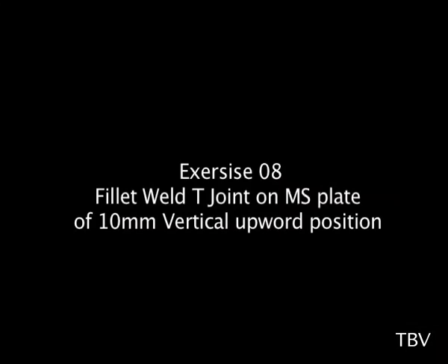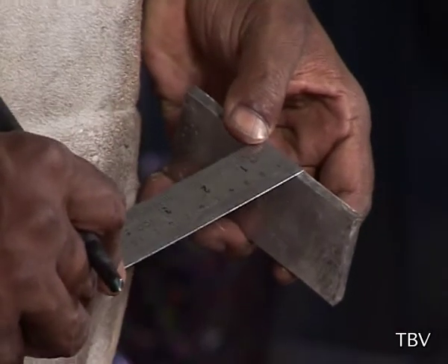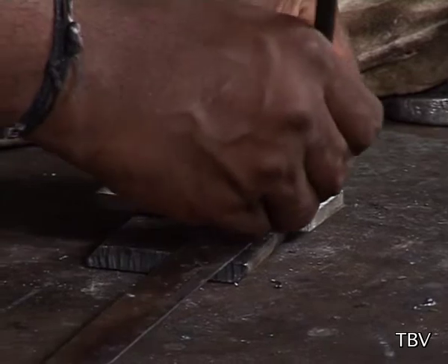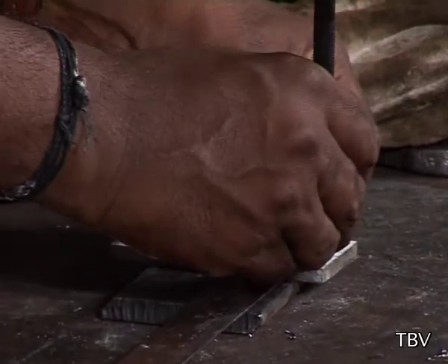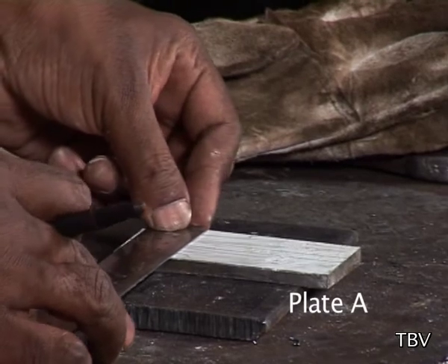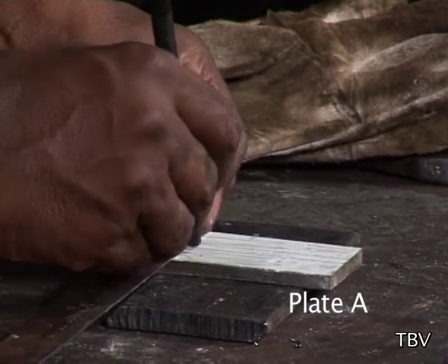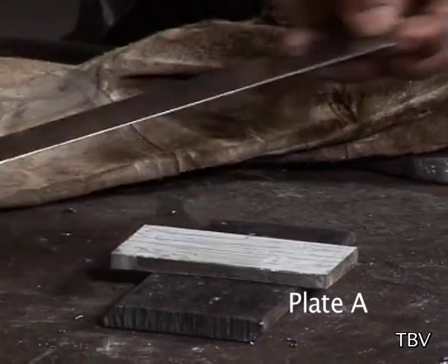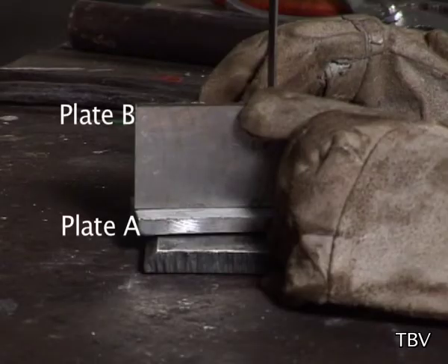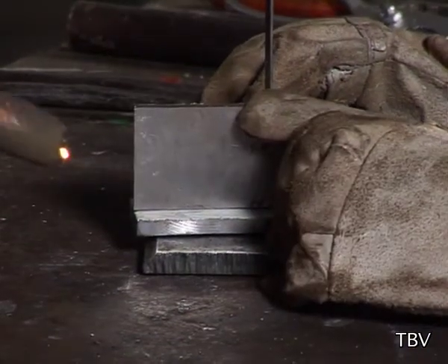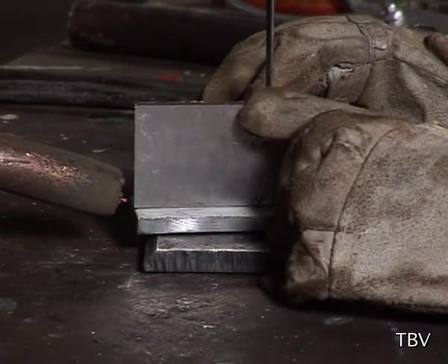Exercise 8. Fillet weld T-joint on MS plate of 10 mm in vertical upward position. By now, you know the preparation of the jobs. Take the prepared jobs. The diameter of the wire spool is the same, 0.8 mm. The welding machine is already on. CO2 gas heater is on 5 to 10 minutes before starting the welding. Set the plate B on plate A in the form of inverted T. Tack weld the two plates on either end, keeping the T-joint in vertical position.